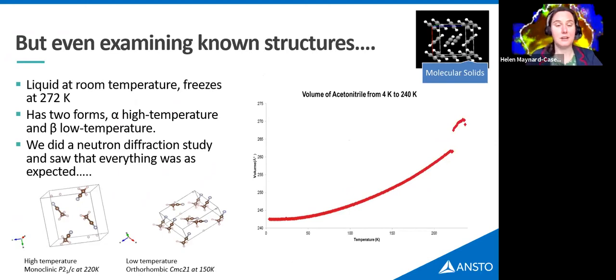But as I said, even for known crystal structures, acetonitrile is probably one of the most used solvents in any lab. And there are numerous crystal structures in that database where it's there as a co-crystal, or as a co-former as well. But we looked at it pure, and they already knew the crystal structures of it, monoclinic and orthorhombic. We did the neutron. Neutrons are generally with bigger samples. Everything was kind of expected.